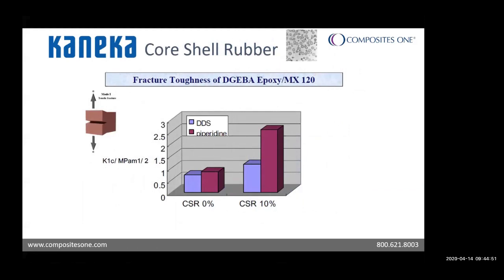Another good toughener out there is the Kaneka core shell rubber particles. They do offer nano-sized particles. It's a simple shear mix into the resin. There's no heating required. And it does have a fundamentally different way of absorbing energy. So these are copolymer spheres, and you can imagine how the crack impinging on the sphere will then cavitate. So picture a rubber ball being pressed down. That cavitation of that shell changes the stress triaxiality at the crack tip, thereby requiring more energy for continuation of the crack. So as you can imagine, we'll see improved toughness, and that's what I want to show here.